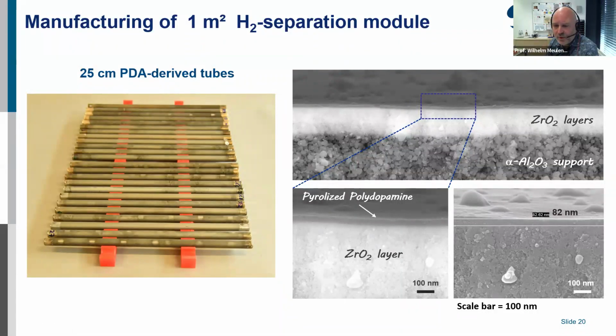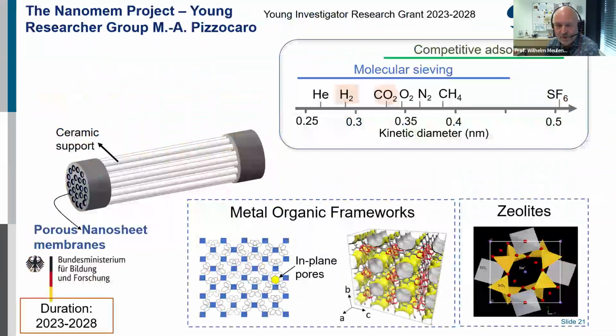A little bit the problem was that in the previous tests, we used a membrane from a Dutch manufacturer. And the pore size of the support is here 18 nanometers. The commercial support we use here from ATEC is in the range of 1 up to 2-3 micrometer pore size. That means we have to make here also some more intermediate or thicker intermediate layers before we coat the membrane on top of it.